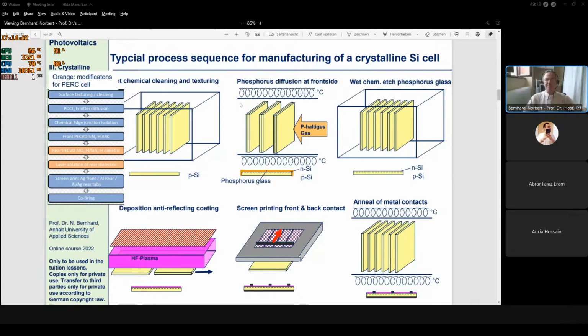The next step is in principle a core step. It's a phosphorus diffusion from the front side, because this makes a PN junction. In this case, you see the wafers are kept back to back. The reason is just to protect the backside against phosphorus diffusion, and also to increase the loading. By this back-to-back loading, we can increase the loading of the furnace by a factor 2. And I should emphasize, there's also a single wafer loading possible, because the phosphorus at the backside in principle does not disturb. It can even improve the performance of the cell by the so-called gettering process. But this is beyond the scope of this lesson. Therefore, I will just mention it at that point, but will not further embark on it in the further course of this lesson.